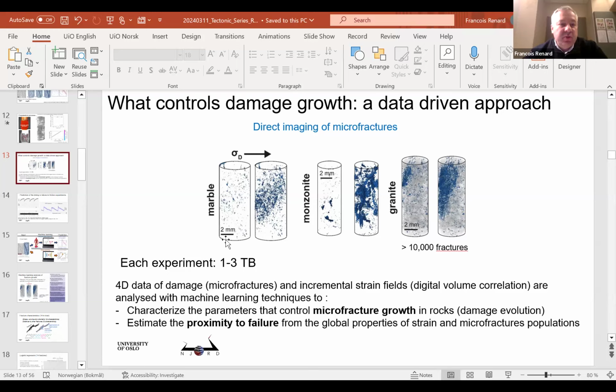So this initial porosity, which has the same gray value as the fracture, is there when we extract it. In all the story I told you, it doesn't have an effect. So it's there, okay. But if we use it or if we don't use it, it doesn't change our prediction of the proximity to failure.